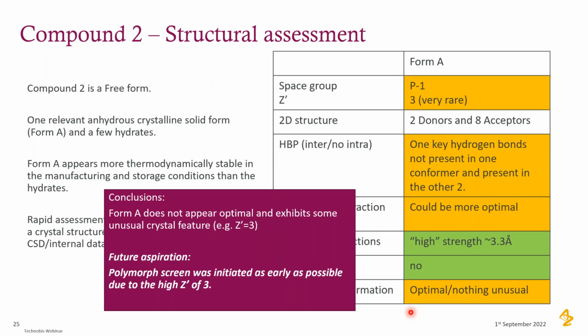So as I said, Form A does not appear optimal and exhibits some unusual crystal features, but unusual doesn't mean it's not stable. It's just for us to kick off the right activity to make sure we understand and can reduce the risks. So we initiated the polymorph screen as early as practically possible to ensure that that form was the one to go ahead with. The main thing is to make sure we're not developing a process which is not actually making the right form and not good for our patients. So that's why we kicked off the polymorph screen early on.